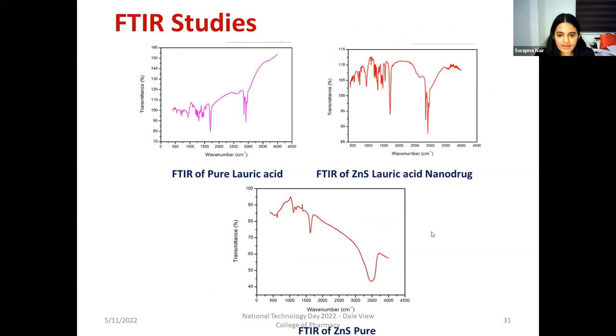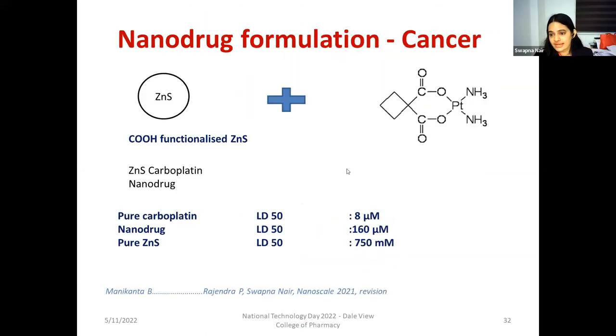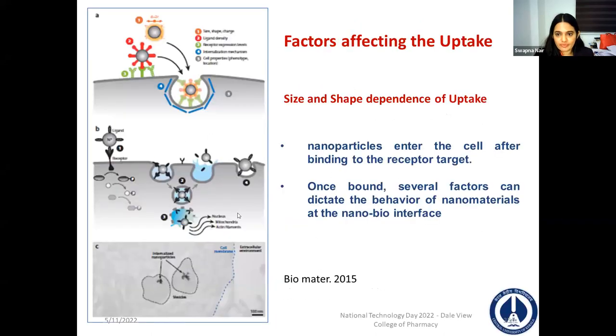So for the anti-cancer, we again tried with the established drugs carboplatin and cisplatin, and we made them with the same zinc sulfide sub-5 nanometer particles, 3 to 5 nanometer size. And we could see the LD50 is enhanced a lot for the nanodrug formulation. So pure carboplatin LD50 was 8 micromolar, while for the nanodrug it got 160. So several orders of enhancement in biocompatibility. It means toxicity is much reduced after the nanodrug formulation. So I'm just leaving these slides. It is the factors that control the uptake and all.